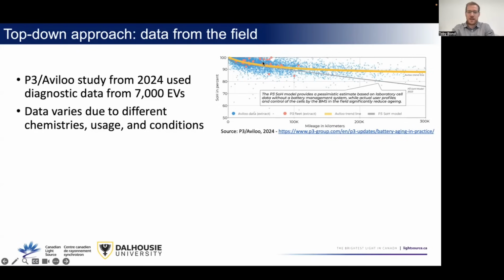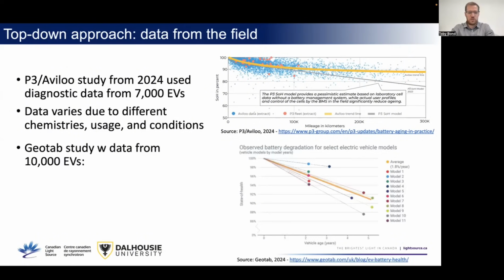And you can see, though, that these dots can vary quite a lot depending on the usage conditions, the model, the chemistry being used. There are a few outliers here that will drop below, and most of these will get caught by the warranty, but it's always a risk. But the average is very much clear. You're still doing really well for cars that were, I think this was from 2019 to 2024.